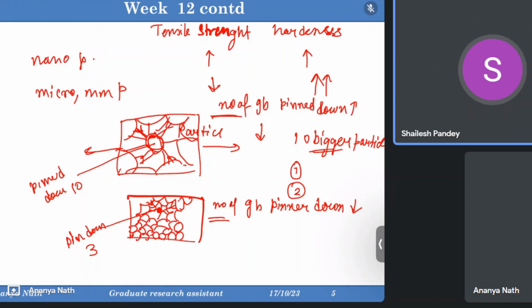Ma'am, I was just reading some papers right now. They have added three different volume percentages of silicon carbide: 5%, 13%, and 20%. In conclusion, in the case of 5% volume fraction of silicon carbide, the tensile strength will increase, and as we increase the volume fraction, the tensile strength decreases. Anyhow, the tensile strength after reinforcement will decrease from the base metal.